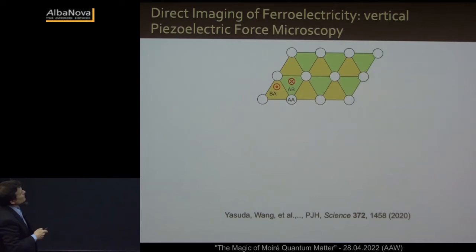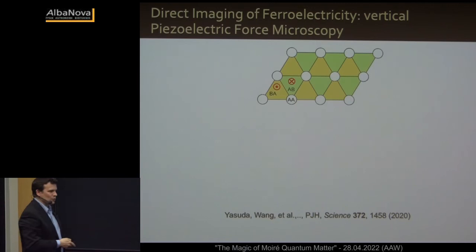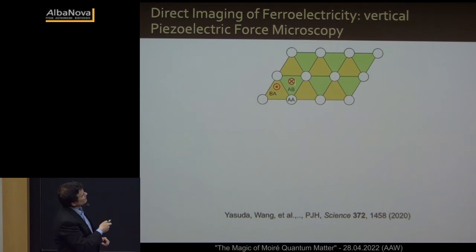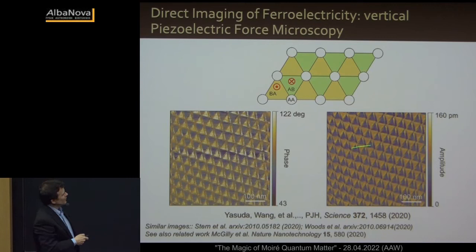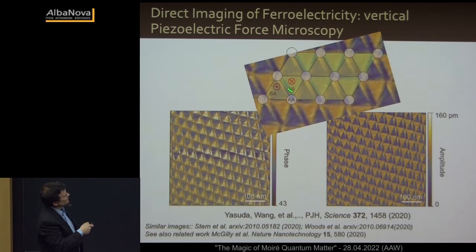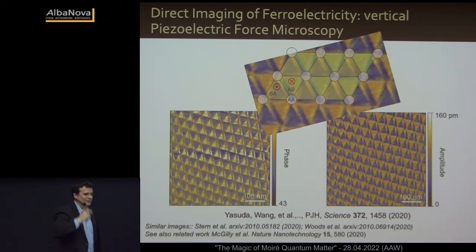In fact, can we have a direct visualization of those Moiré patterns, anti-ferroelectric Moiré patterns that I told you about? Indeed, we can. We can use a technique called piezoelectric force microscopy, and we can measure directly the electric dipole moment in these structures. And you can see here in the phase and amplitude image, this beautiful honeycomb structure. You can put it on top of these, and you can see the honeycomb pattern of electric dipole moments up and down. Okay? This is something that works at room temperature.